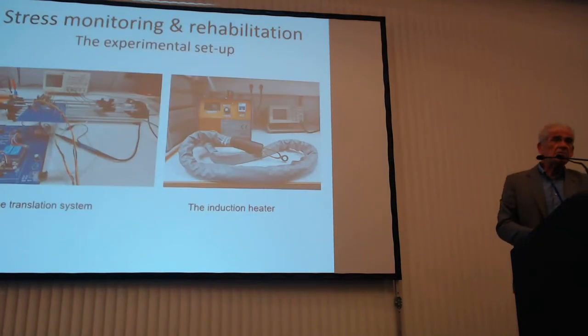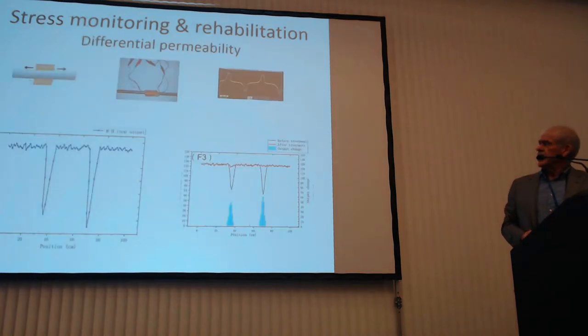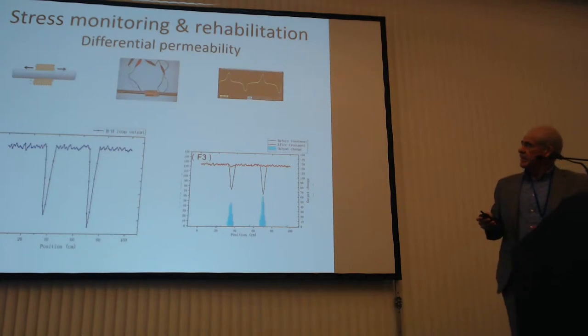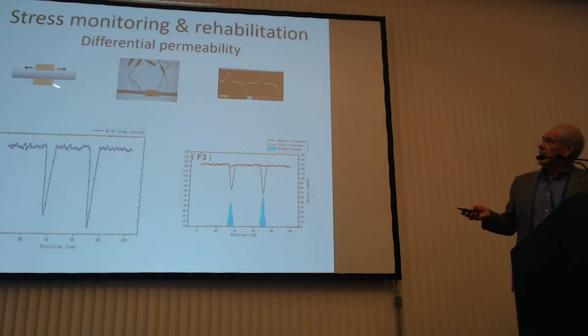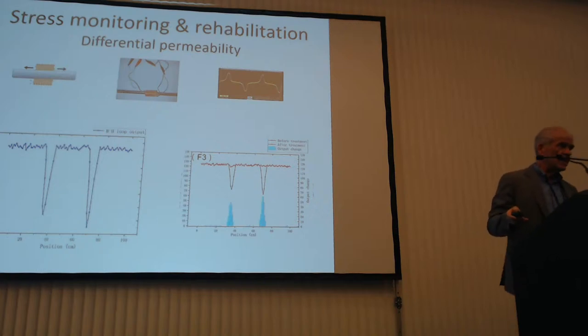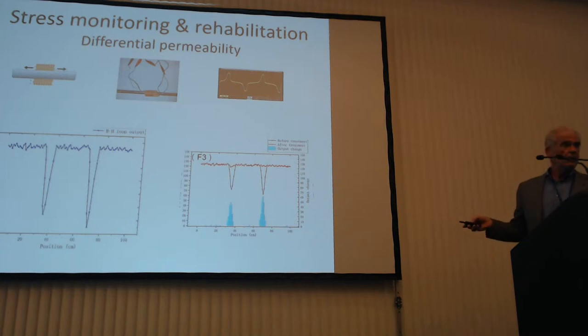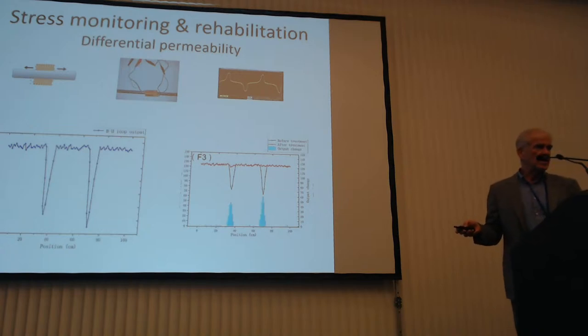An example of that has been done in the laboratory, performing tests using induction heaters either bought from the market or developed by us. So you can see here that using permeability measurements, a simple permeability sensor, hammering steel in different positions results in a decrease of permeability, as you can see in this slide. Then, by applying localized heating, not heating all over the steel, there is a coming back of the permeability, which means that the residual stresses have been released in both